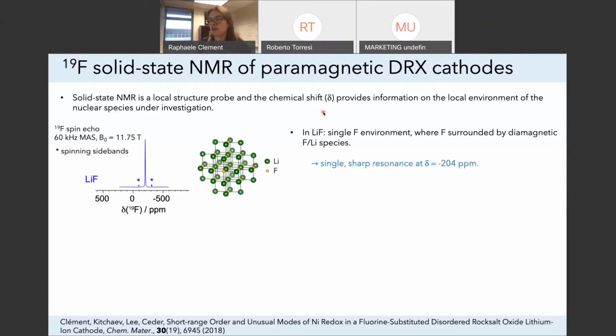So if we start with a very simple example here, this is lithium fluoride. This is the environment of fluorine in this material. So we have fluorine here in the middle, and this is a 5 angstrom sphere around this fluorine atom. So this is its local environment. And that local environment dictates the chemical shift that we see in our spectrum here. These asterisks above these little signals mean that these are sidebands. And so this is the main peak that you should focus on here. So in lithium fluoride, you have a single fluorine environment, which is surrounded by diamagnetic species only. So you have this very sharp signal at a chemical shift of -204 ppm.